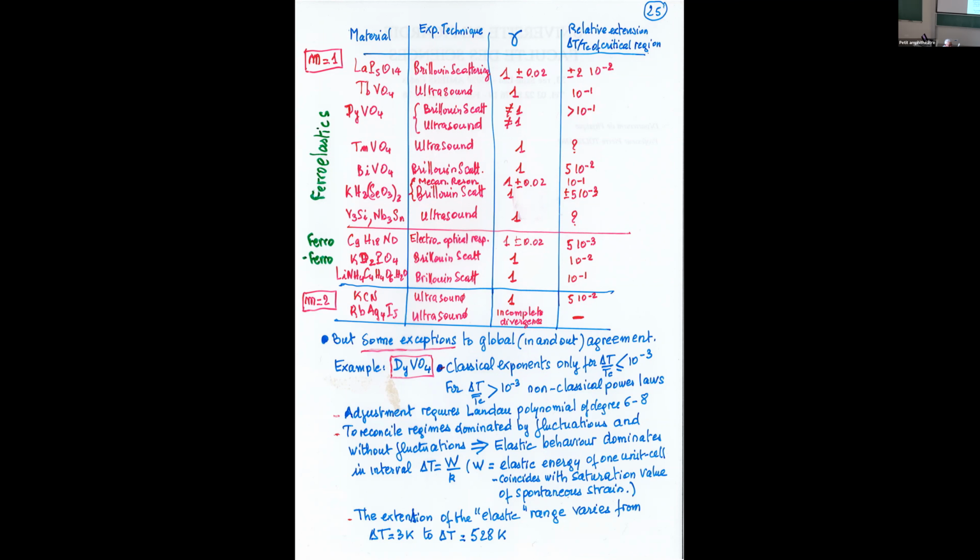No, it's not related to the symmetry. It's related to the form of the strain. If you have tensile strain, then it's more or less uniaxial in direct and in the reciprocal space. But if you have also shear strain at the same time, then you necessarily have some planes. You see, it's a plane which is deformed.